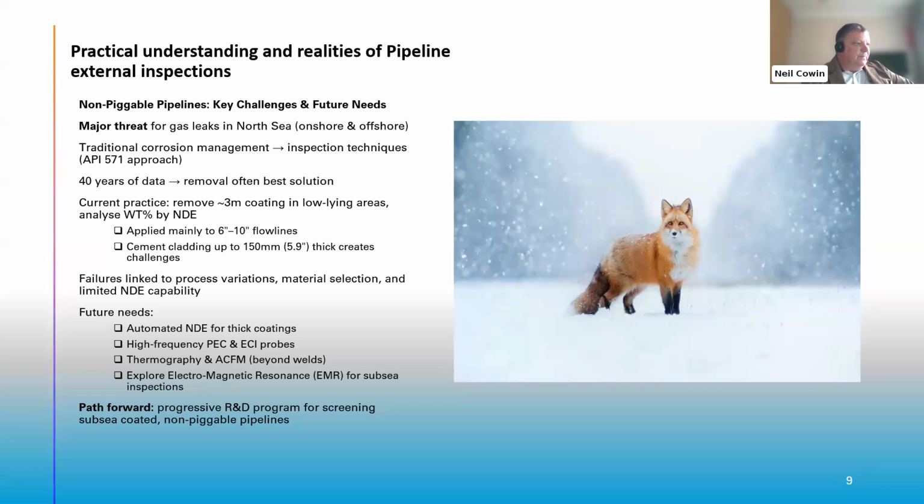The other beauty that I've found with Pulsed Eddy Current is that you can see through the pipeline in quadrants. I can put it on the top of the shell, 180 degrees, and still also be seeing the underside if it's partly buried. So that's an efficiency thing. As far as wall thickness is concerned, I've never had too many issues with it. It'll stay within the plus or minus 3% range.